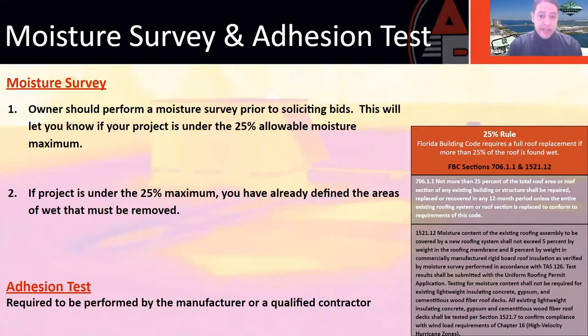How are these moisture surveys done? Typically, when they're making the assessment, you get a hired consultant who will go out and implement certain tests on the roof in order to determine whether there's moisture trapped within the assembly. Some of those tests are moisture scan through electrical impedance. They use an electrical current, pass it through the roofing system to see if there's any fluctuations that would indicate that there's moisture trapped in those areas. They use a thermal scan using infrared or FLIR technology. That's using the heat scanner to see where there's warm spots and cold spots, again indicative of areas of trapped moisture. There's the nuclear roof moisture gauge, which is a little more accurate than the thermal scans, and can be used in conjunction with the other two to determine where the moisture is in the roof.